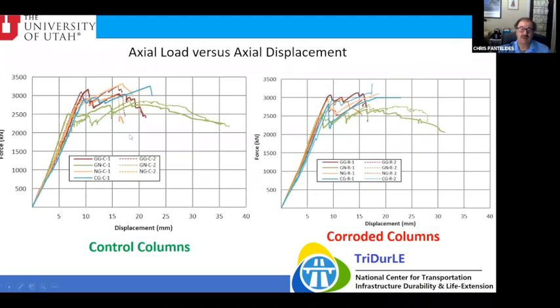Here's a comparison of all the control columns, including all four different types. And you can see again, the ones with the stainless spiral actually display quite a lot. As far as the peak load, they're all pretty much in the same range. Perhaps the ones with stainless verticals do a little bit better than the others, but pretty much in the same ballpark. And then here you can see the ones exposed to the water. They all drop compared to their control counterparts. But again, we see that the one which has the stainless steel spiral is the more ductile of the specimens.